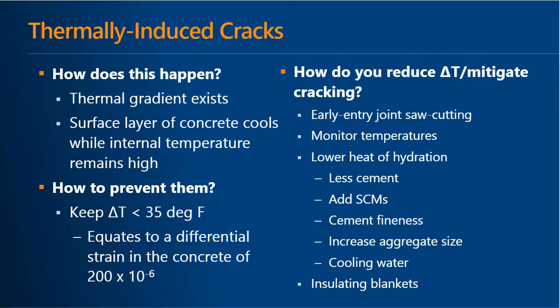So thermally induced cracks form when a thermal gradient exists, such as when the surface layer of the concrete cools, but the internal temperature stays high. So for example, you have your heat of hydration from cement hydration within the interior of your concrete, but your exterior surface, your exposed surface, is exposed to diurnal and seasonal temperature changes. And so you can get a thermal gradient that exists between your exposed surface and the interior of your concrete body.